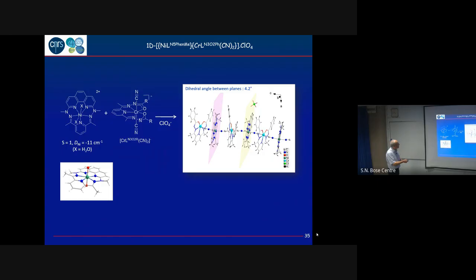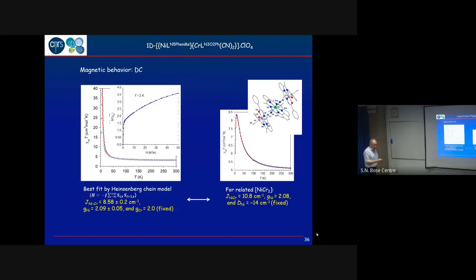I took the pentagonal plane as a reference, and you can compare the angle between the plane in pink and the plane in yellow, and you see that they are almost parallel. So we have just 4 degrees. So this means that now the anisotropy axis that is perpendicular to that plane, these axes will be aligned with the same direction.